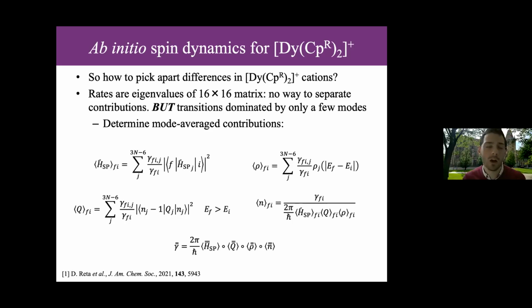So for instance, I could say, okay, let's take the spin phonon coupling from the original dysprosocenium, but pair it up with the average number of modes for each transition from Jeff Long's, one of Jeff Long's molecules. Or I could take the density of states, so how close your energy levels are, from Layfield's molecule, and put them with one of Jeff Long's, or whatever you want, and see how that changes the rates. So comparatively, you can start to think about how you are switching out different parts and changing the dynamics, and therefore making comparisons between what's important.